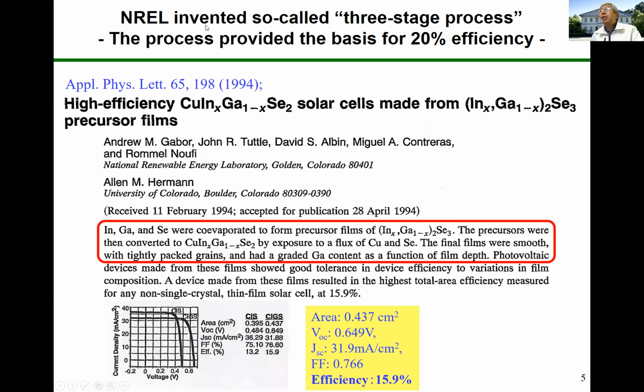NREL invented the so-called three-stage process. The process provided the basis for 20% efficiency. Indium, gallium, and selenium were co-evaporated to form a precursor film of the (In,Ga)2Se3 phase. The precursor was then converted to chalcopyrite copper indium gallium diselenide by exposure to a flux of copper and selenium. The final film had a smooth surface with tightly packed grains and graded gallium content as a function of film depth. They achieved 15.9%.